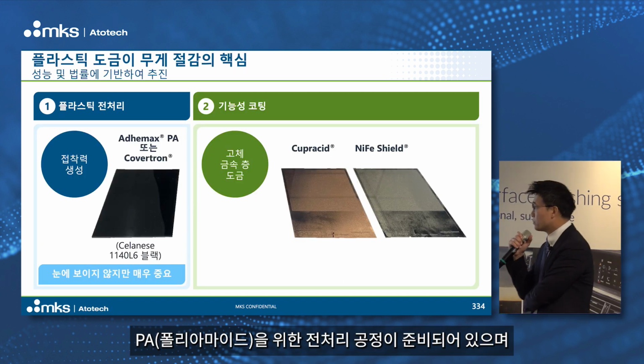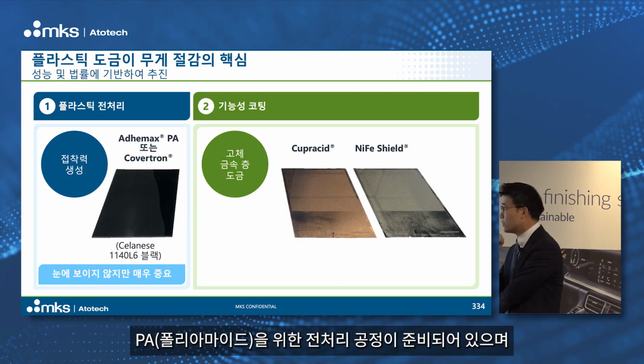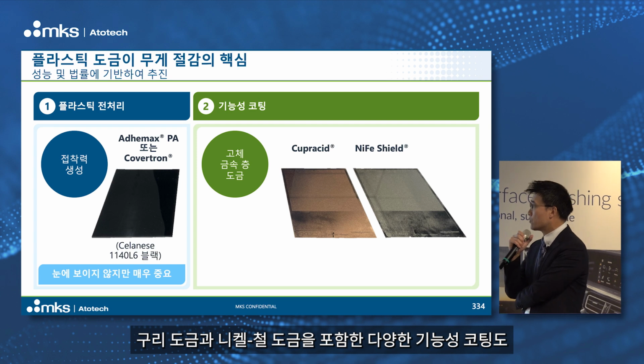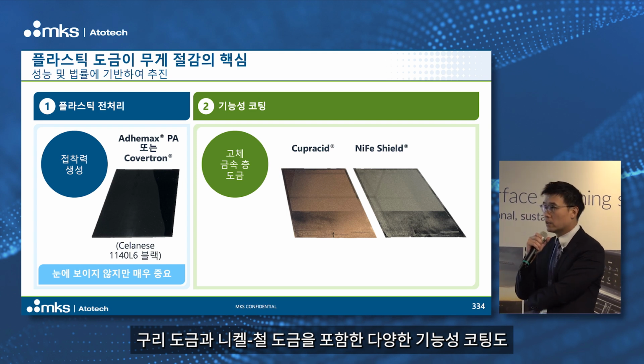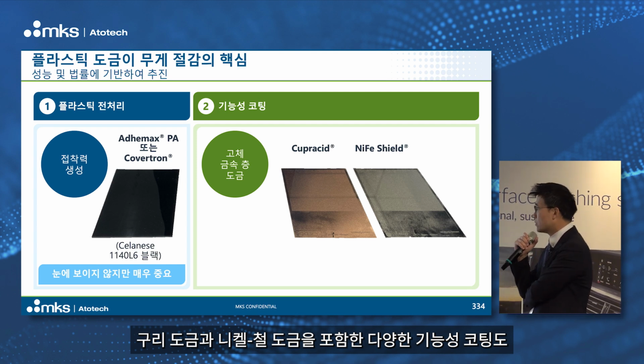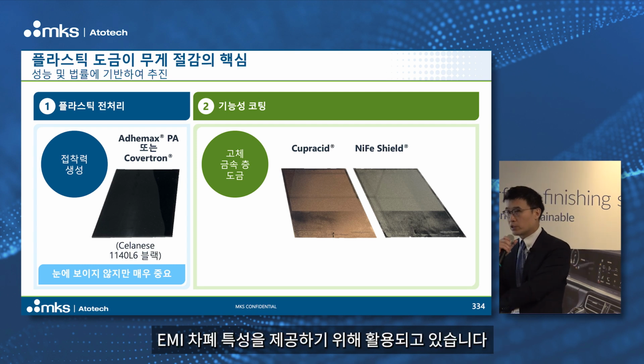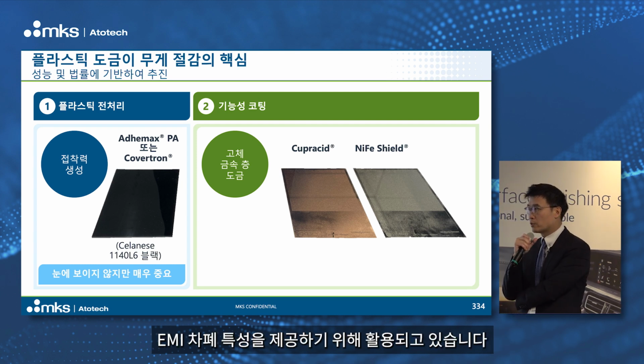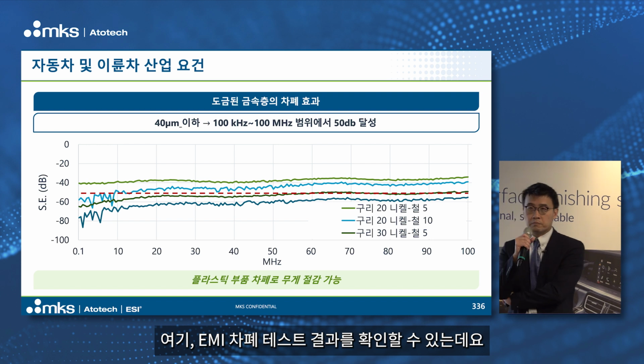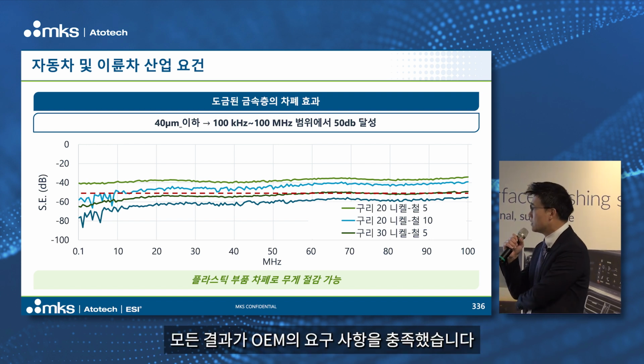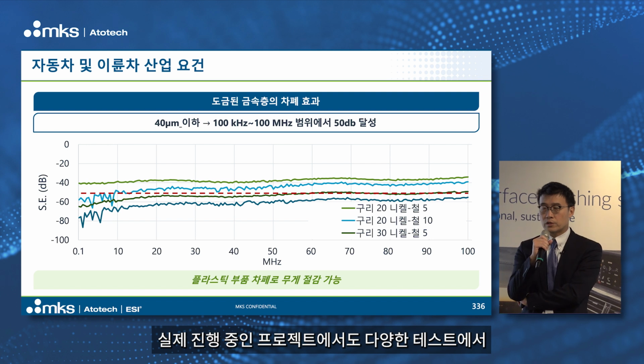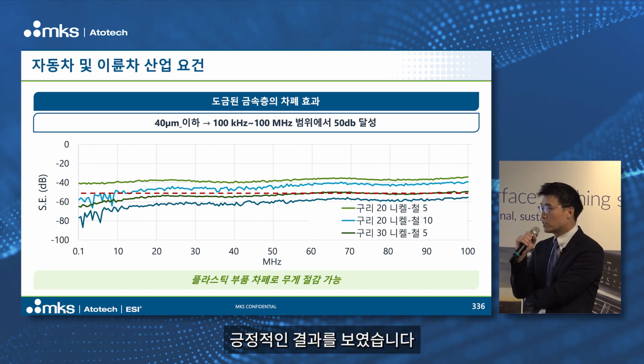You can see we have a pretreatment process, especially for PA. And then also, of course, we have all these functional coatings, which are copper plating, and also nickel iron plating, which are available for the EMI shielding property. Here you can see the EMI shielding test result, and it's all passing the requirement of the OEMs. And we have real projects which are doing a lot of tests, showing positive results.